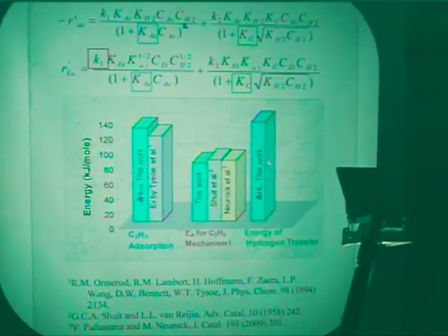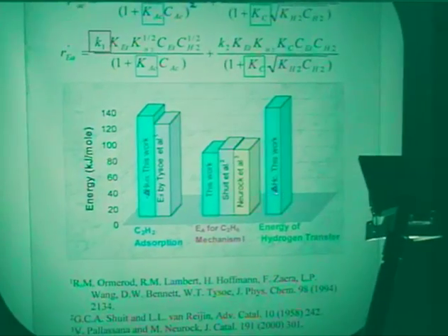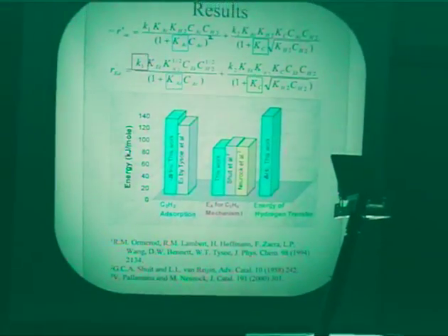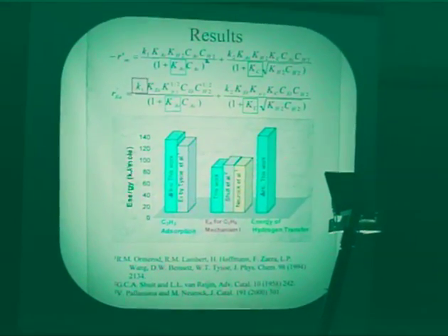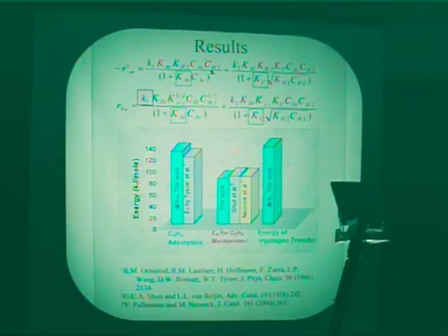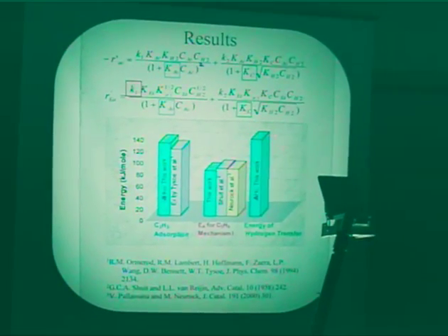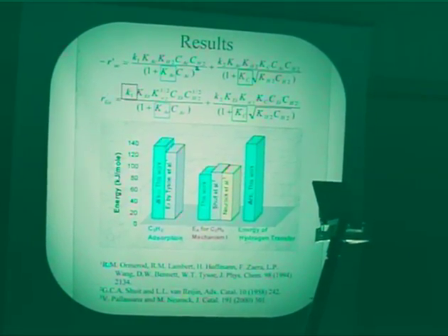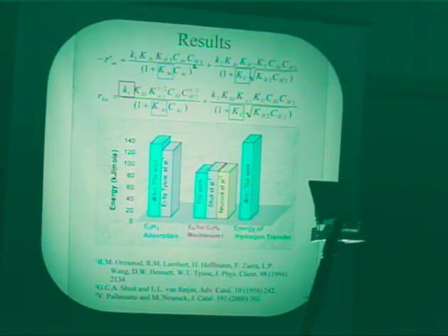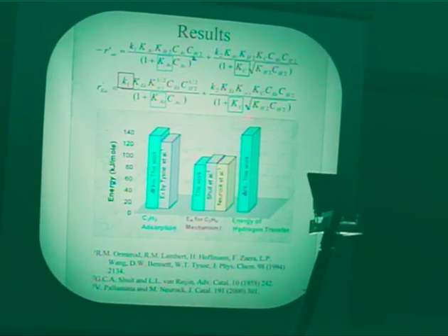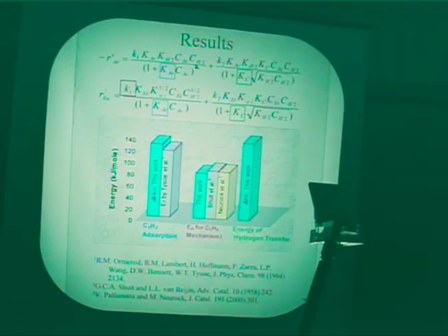So in total, the last one is the enthalpy of hydrogen transfer, and I couldn't find a comparative result. But for this work, it's about 135 kilojoules per mole. And notice that it's endothermic. That makes sense because the second mechanism didn't come about until higher temperatures, so it takes energy in order to activate this step.